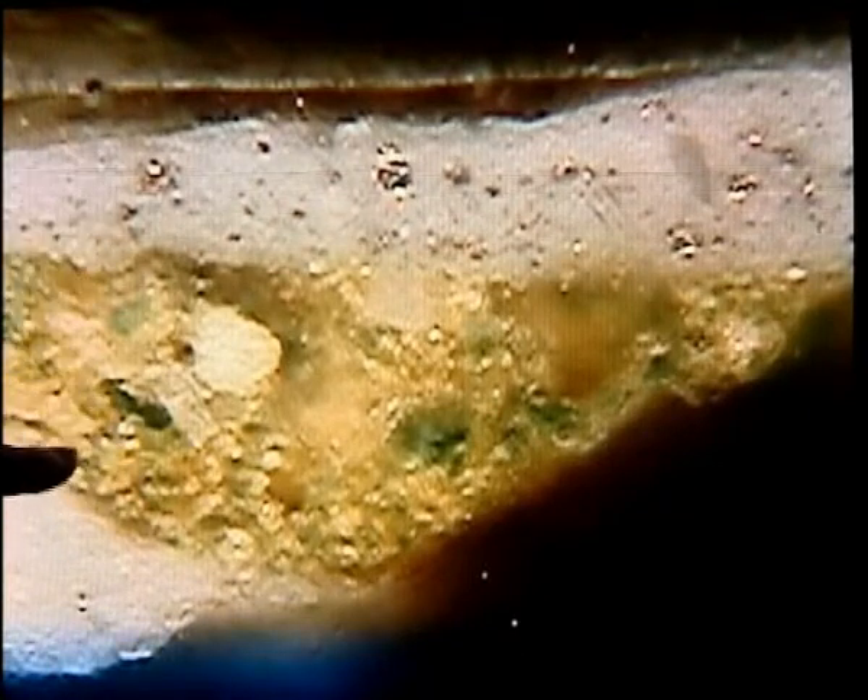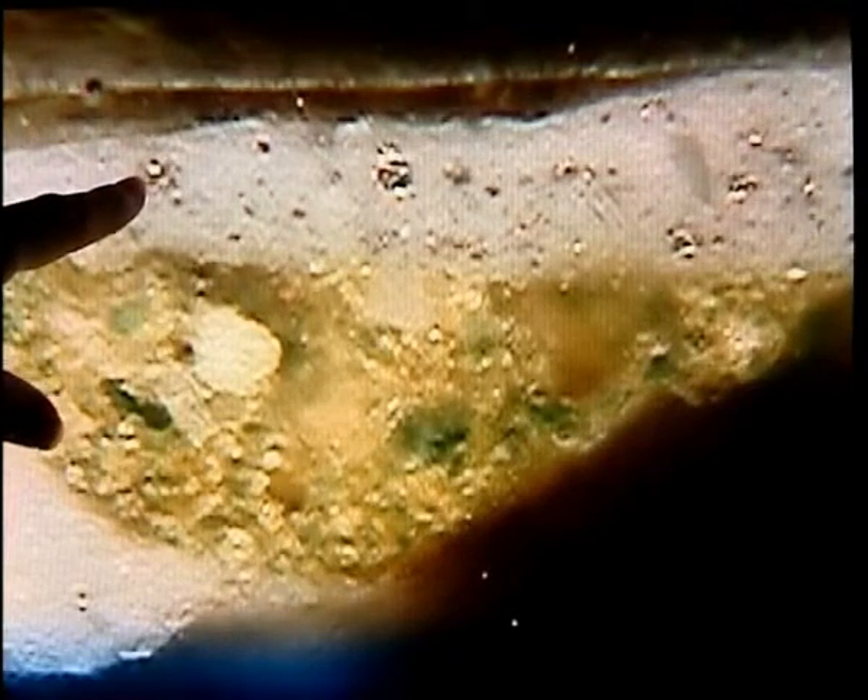What we can see is that the grey paint lies over green landscape paint, and we can see immediately that Raphael changed his mind during the painting. We can also see the separate pigment particles within the paint layers, so we can see what mixtures Raphael used. In the grey paint there is a mixture of a white pigment with another pigment which looks like tiny particles of metal. But in order to identify that pigment, we're going to need to do some more sophisticated analysis.